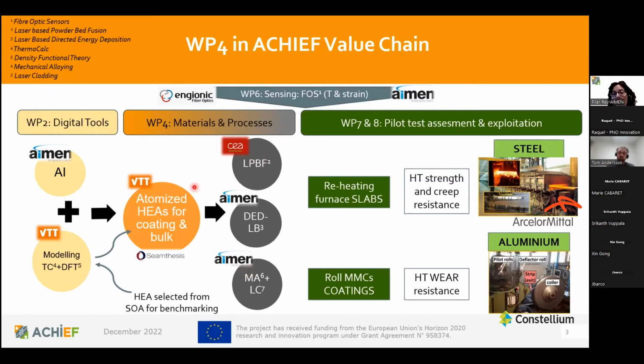So the application of this process will be in two sectors. One is steel and the other aluminum. These sectors are represented by, in the case of steel, ArcelorMittal, and in the case of aluminium, by Constellium. So in the case of Arcelor, we will create some parts for a reheating furnace. And the idea is to improve the high temperature strength and creep resistance. Together with this, in this application, we will use sensors for the monitoring of the temperature and the strain. And we will introduce these fiber optic sensors in a coating made with these high entropy alloys. In the case of Constellium, the idea is to apply these metal matrix composites based on HEAs in the rolls in the aluminum process in order to increase the wear resistance at high temperature.